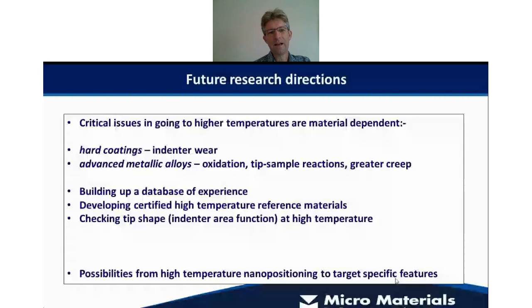So as we go to higher temperatures, the critical issues, provided we have a stable system, and in Nanotest Extreme we have a particularly thermally stable system, we don't really need to worry about thermal drift particularly. Then the remaining critical issues are really material dependent. These split typically into potential problems with indenter wear for hard coatings, and metallic alloy systems, typically we need to, say, do the testing under high vacuum to eliminate oxidation. We need to consider various different tip-sample reactions that may be more likely at higher temperature, and we need to account for this higher level of time dependency and plan our indentation tests and the analysis accordingly.